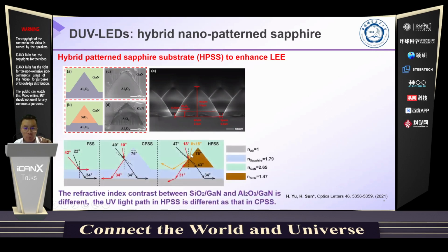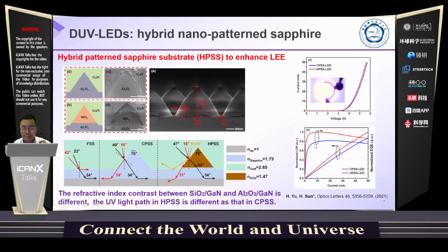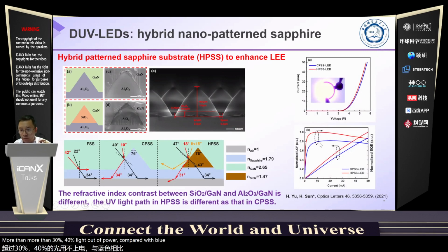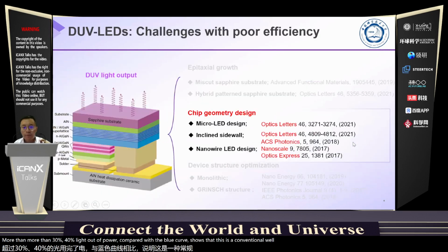Here we introduce a hybrid patterned sapphire substrate. Basically, we combine silicon oxide with gallium nitride and aluminum oxide with gallium nitride. We introduce a large refractive index contrast between these, and more light can escape from the sapphire side. What this leads to is that we boost the light output power by more than 30%, 40%, compared with the blue curve, which shows the conventional one.